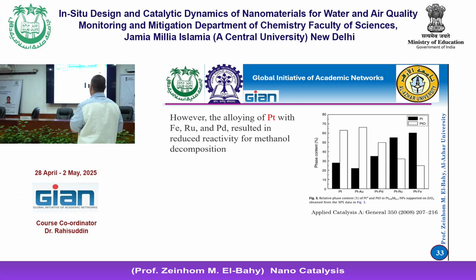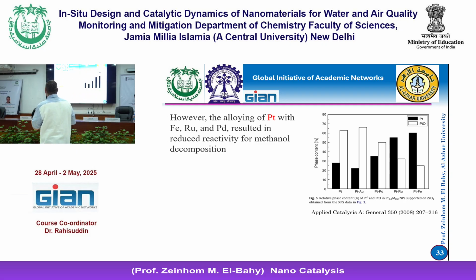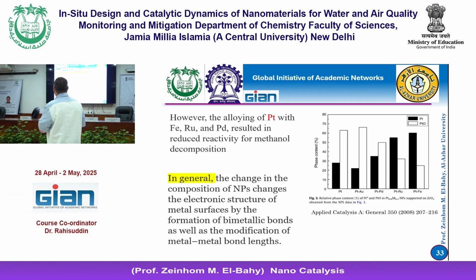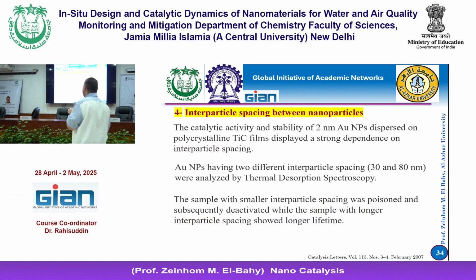This is an example data, where the alloying of platinum with iron, ruthenium, palladium, here there are two, platinum and platinum oxide. In the case of platinum, the activity of platinum itself is higher than the alloying. And in the case of platinum oxide, it is a different attitude, different behavior. In general, the change in the composition of nanoparticles changes the electronic structure of the metal surface by the formation of bimetallic bonds as well as the modification of metal bond lengths.